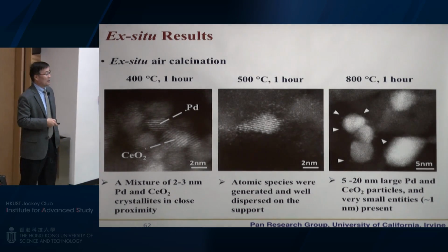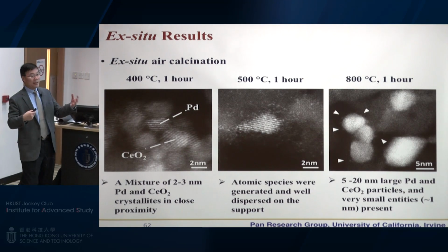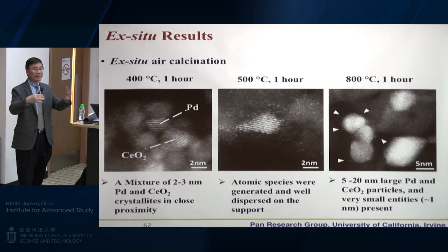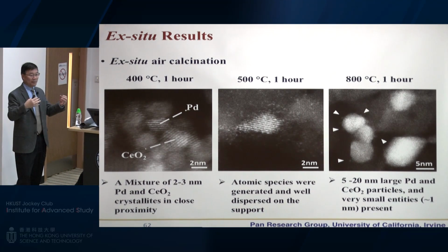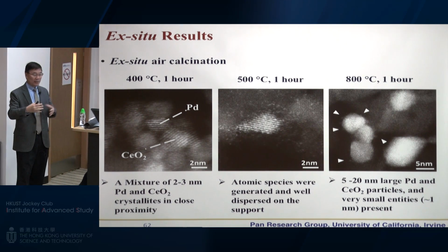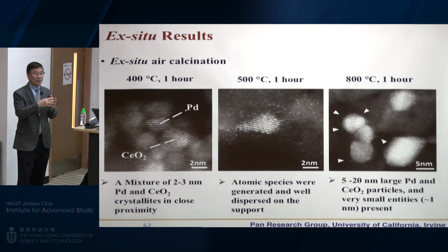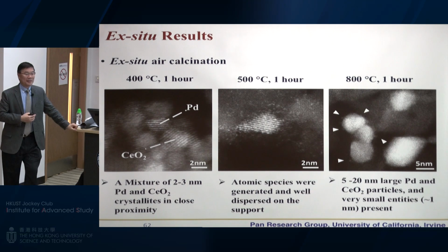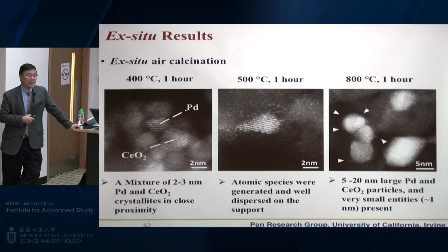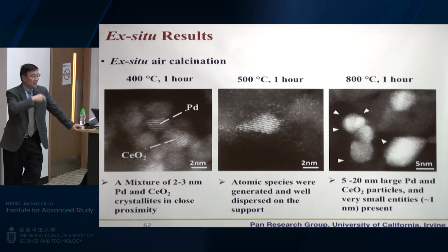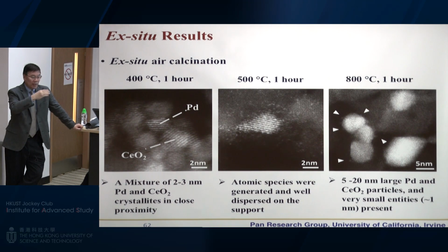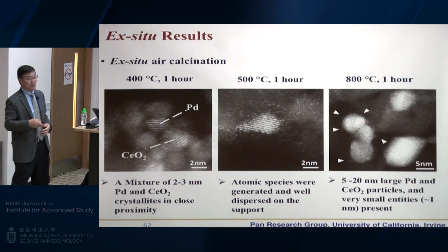Then he said, now you have this gas cell, can you put it in, do the same treatment as he did, and see how this core-shell structure looks like in situ. But in the end, he doesn't have this predicted core-shell structure. Basically, it's just a mixture of two kinds of particles, metal particles and oxide particles. But after reaction, a very interesting structure is stabilized, and that has enhanced activity. So that's basically just one thing.